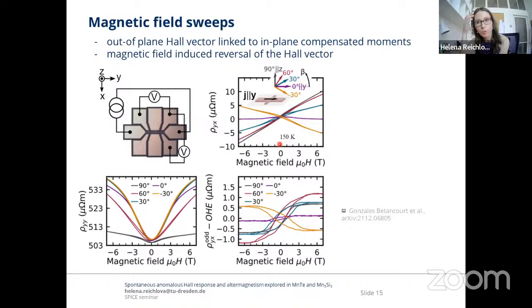No, with this material, we didn't test different quality samples. With the Mn5Si3, we basically report a new magnetic phase in the thin films, in some sense, right? That it's different from the bulk. So we feel much more responsible for testing it via all possible ways, to show where our effect comes from. With the manganese telluride, we feel much more confident that the magnetic and structural characterization was already done many times. So there we didn't put so much effort into measuring different quality of samples.